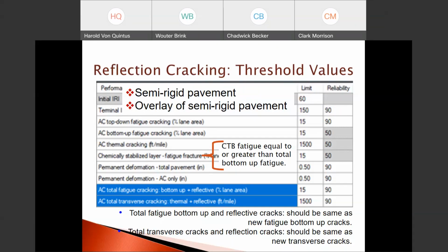And the reason why it's generally suggested that the CTB fatigue, in terms of fatigue fracture, could be greater than the total of the bottom-up fatigue is that it does take time for any fatigue cracks in the CTB layer to propagate through the asphalt overlay, so they may not always be observed once the cracking starts in the chemically stabilized layer. So in general, about 15% sometimes is suggested for the CTB fatigue layer.